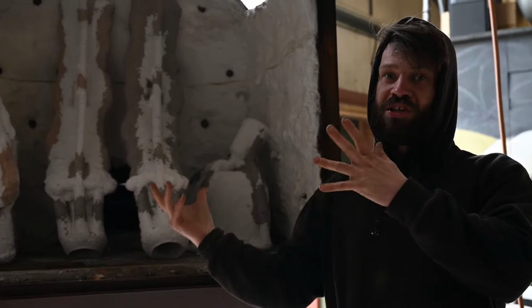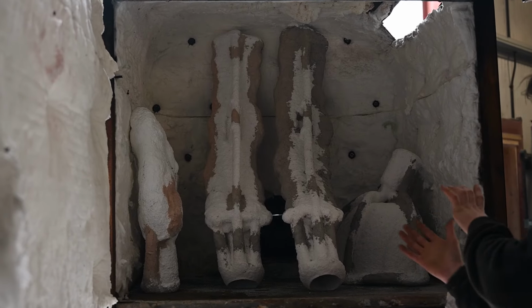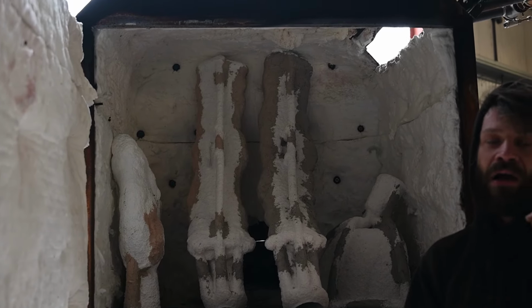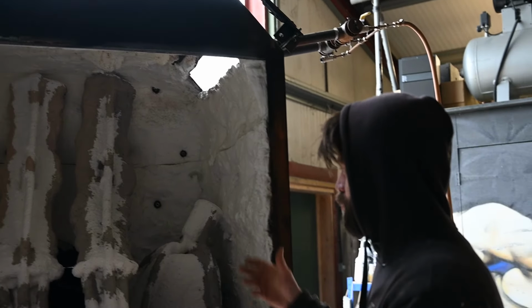The reason for that is because if you poured molten bronze into a cold shell, the bronze tends to solidify a lot faster. Therefore, all of the detail, or those hard to reach places, tend to get missed. So we like to get our shells red hot, and we like to pour our bronze at about 1100 degrees into a piping hot shell, and that gives you your best casting results.